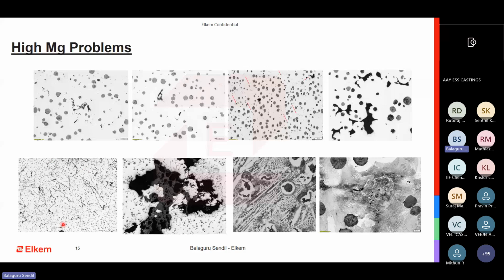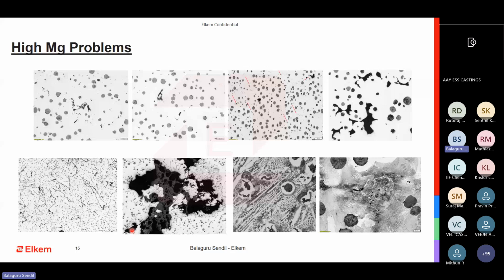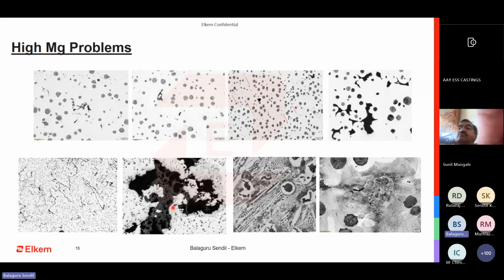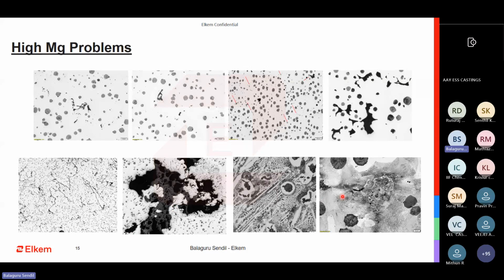So this dross is a very, very classic example of magnesium being on the higher side, especially the free magnesium. And slag is also quite possible, and then carbides. So when you keep the magnesium higher, these are the problems that you might get. Not always, but quite high. And when it comes to casting yield optimization, this is a very dangerous image to have. So the shrinkage, if it is small, it is okay. It can be managed to some extent.